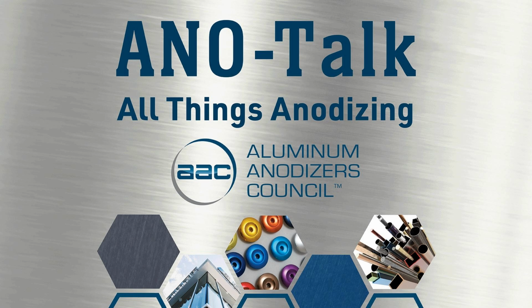decrease the process time even more, for example, in hard anodizing, because you really want to create a very hard layer. But then you of course need to make sure that your contact points are able to draw the current. And you also need to have a well agitated, maybe even better agitated, as we were talking about with the cooling. So definitely in type 3, there are some possibilities also to change the properties a lot, because doing the hard anodizing, also type 2,